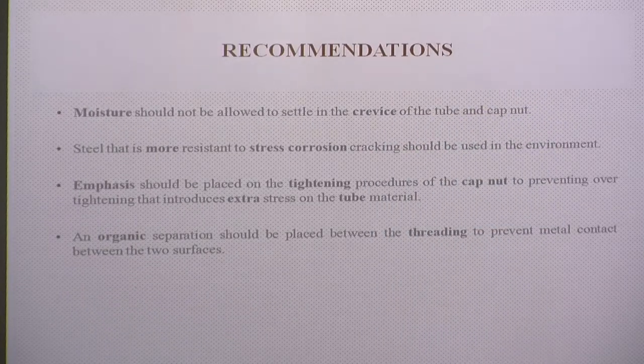So the recommendations here: moisture should not be allowed to settle in the crevice of the tube and cap. Once moisture settles in, that's a problem. Steel that is more resistant to stress corrosion cracking should be used, or emphasis should be placed on tightening procedures of the cap nut to prevent over tightening, because it puts extra stress on the material. You need to follow your procedure to tighten it. Another thing is to put in an organic separation, placed between the threading to prevent contact between the two surfaces.